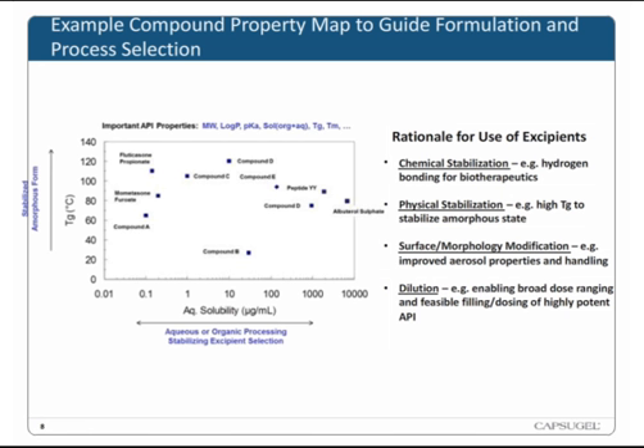Physical stabilization: oftentimes if we're trying to augment a lower TG and stabilize the amorphous state, we'll add something with a bit higher TG. Surface morphology modification: putting in hydrophobic, amphiphilic materials that go to the surface of the particle and create less resistance for particle-particle adhesion and improve dispersibility. And then oftentimes these molecules are very potent and we don't need to get very much into the lung, but you still need to have enough powder that you can accurately weigh and put into your capsule and have come out in a reproducible way. And so we oftentimes have to put excipients in just in terms of dilution, and in this case we like to look at the most safe and well-precedented materials. And so that discusses our thought process around formulation.